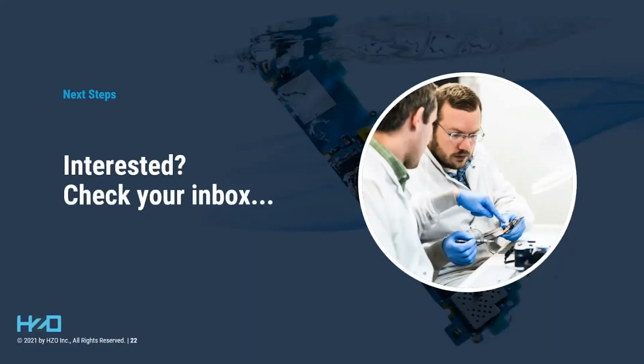In what time frame does corrosion start affecting a PCB? Corrosion can start to impact a PCB immediately. It may not be visible and it may not have an impact on electrical properties or signals immediately, but the metal at the substrate starts to react as soon as it's exposed to water and ions and voltage. Typically, this shows up first as just a bit of oxidation, but the dendrite formation can start to occur in as little as 10 minutes in a way that is capable of forming shorts.